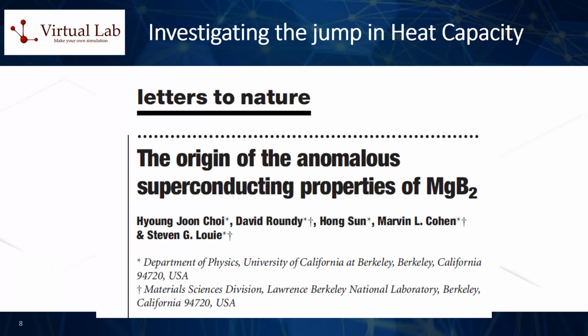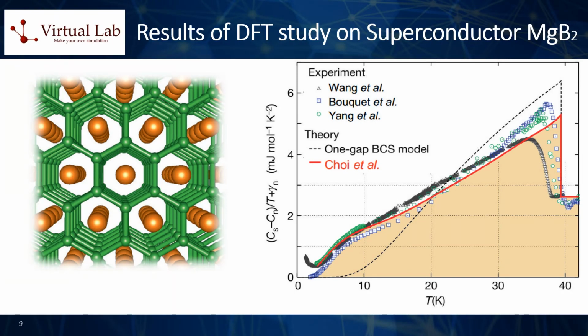In a study performed in 2002 by Professor Choi and co-workers from the University of California, Berkeley, the experimentally measured evolution of the temperature-dependent heat capacity of magnesium diboride was directly compared with the same curve obtained from ab initio computational methods, through an implementation of the aforementioned Migdal-Eliashberg theory of superconductivity. The main results of this computational investigation are portrayed under the present slide.